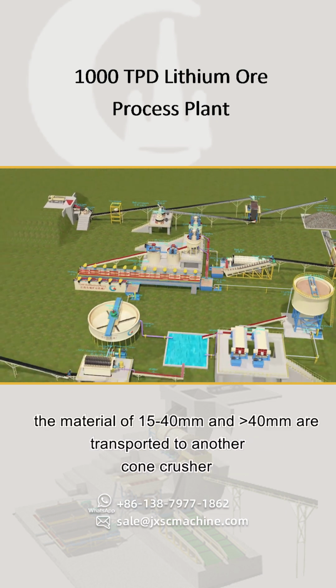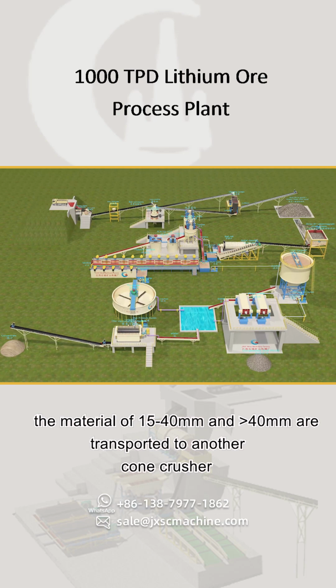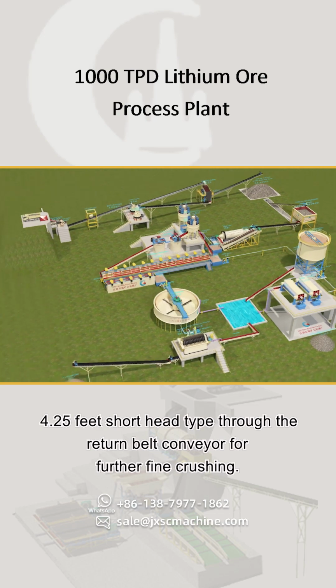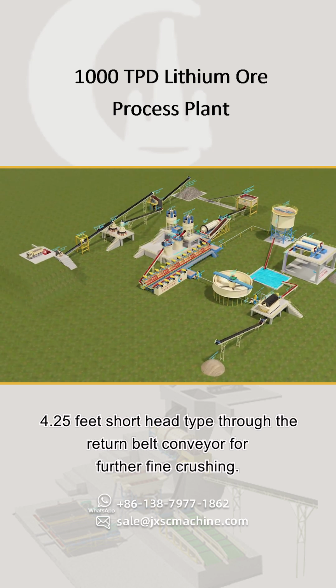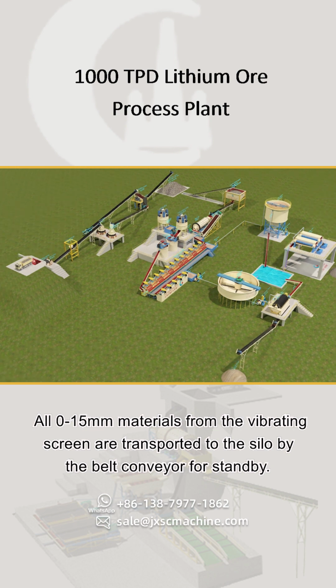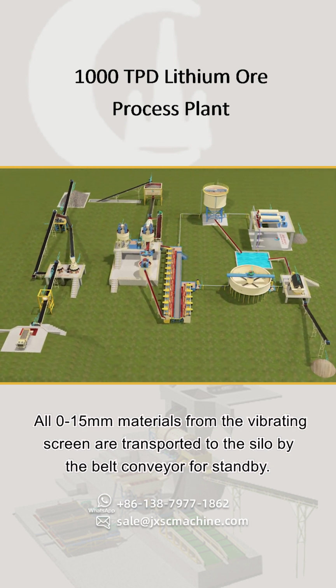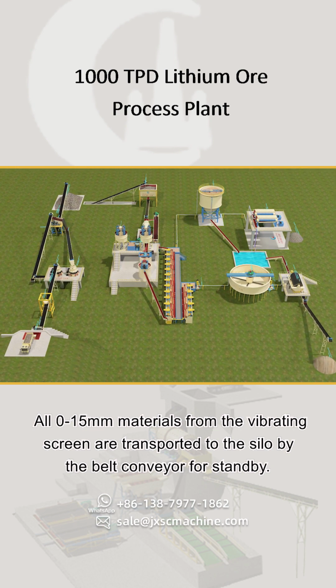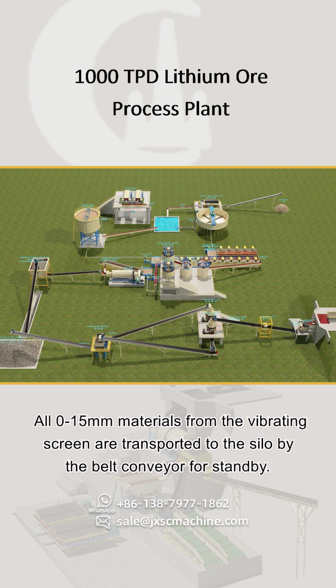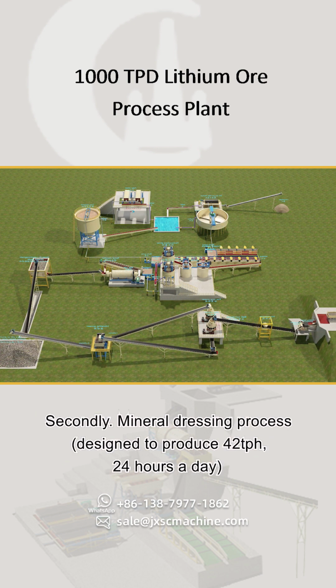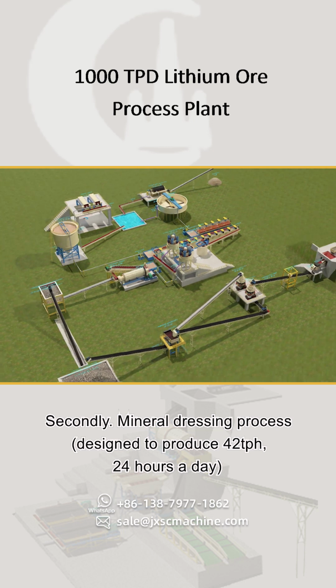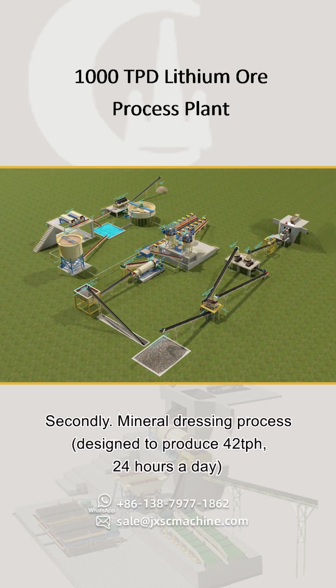The material of 15 to 40 mm and more than 40 mm are transported to another cone crusher, 4.25 feet short head type, through the return belt conveyor for further fine crushing. All 0 to 15 mm materials from the vibrating screen are transported to the silo by the belt conveyor for standby. Secondly, mineral dressing process. Designed to produce 42 tons per hour, 24 hours a day.